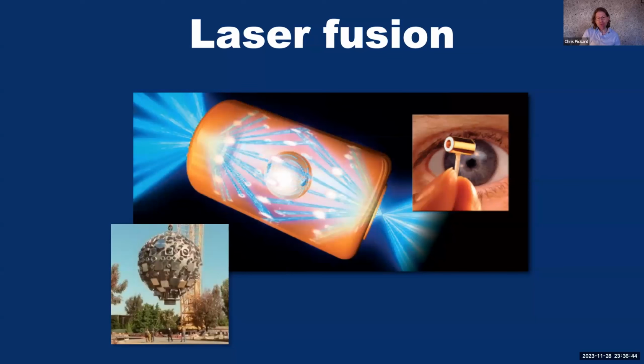And the reason for that was that the pellets that they're using for laser fusion in the National Ignition Facility were actually often largely carbon-based. And they were very concerned about phase transitions that might happen on the route to laser fusion ignition, or inertial confinement ignition.